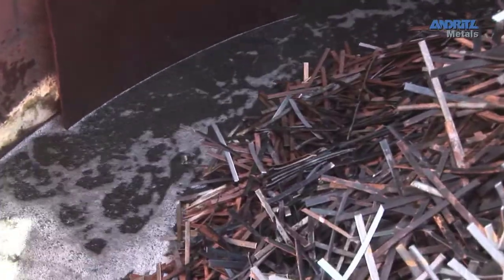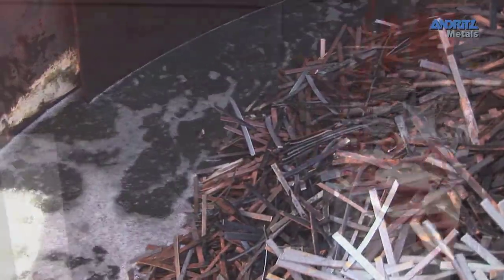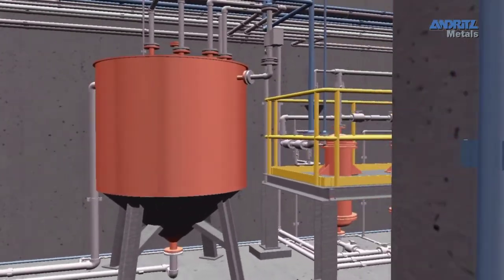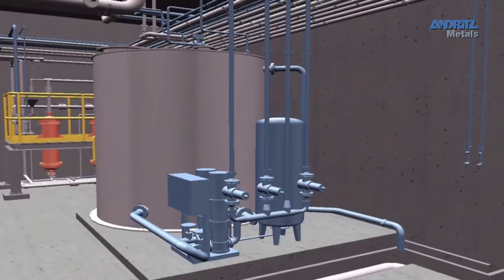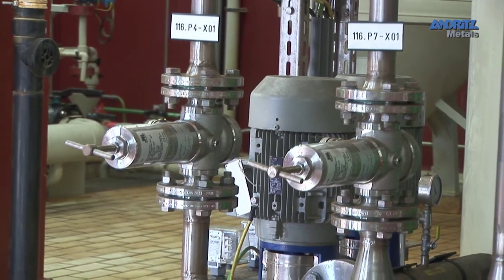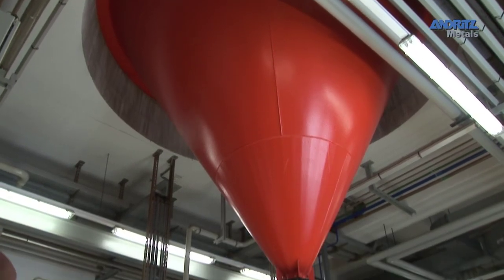The material is not wasted. The overflow from the leaching column flows via gravity to the ammonia process bin. In the next step, the pickle is adjusted to a specified pH value through an exactly added dose of ammonia and iron hydroxide is precipitated. Additionally, fine air jets are blown in so that a lesser part of the iron hydroxide is oxidised. On these iron hydroxide particles lies the undesirable silicon oxide which exists in the pickler.